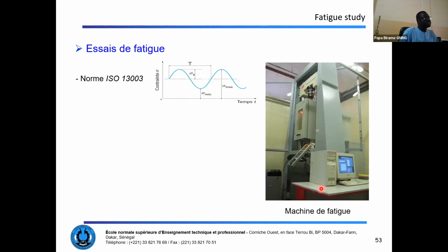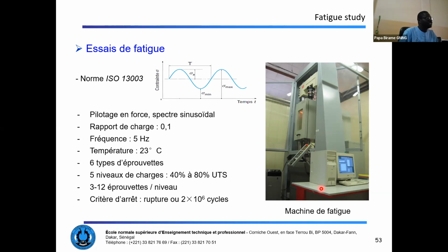So next study that was done is the fatigue behavior of these composites. It was sinusoidal loading with a ratio of 0.1. The frequency was around 5 hertz, the temperature was regulated to 23 degrees, and the loading levels were between 80% of the ultimate tensile strength to 40% of the ultimate tensile strength. And at each level, 3 to 12 specimens were tested. The target was to reach 2 million cycles before stopping the test.